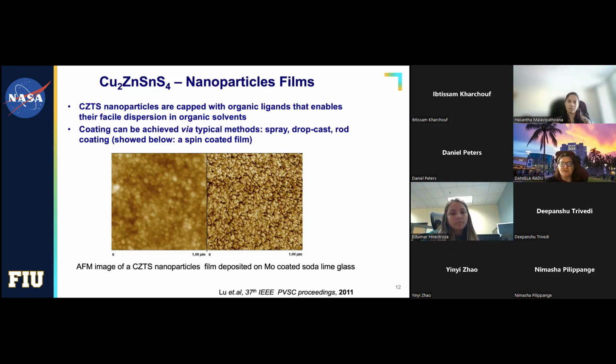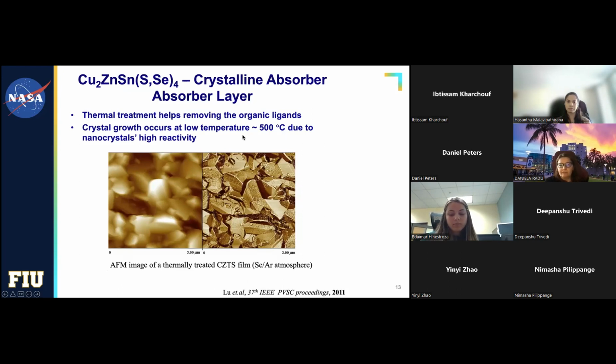with some environmental safety protection. But the bottom line is that I'm taking these materials, as I compared earlier with the chocolate chips, and I subject them to 400, 500 degrees Celsius. This particular sample has been annealed at 500 degrees Celsius. And look what's happening. I'm jumping from about 20 nanometers diameter to about 1.5, 2 micron particles, large crystals. These are able to function in a cell, as I showed earlier, to conduct electricity.